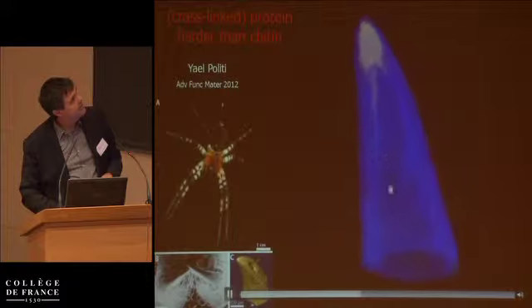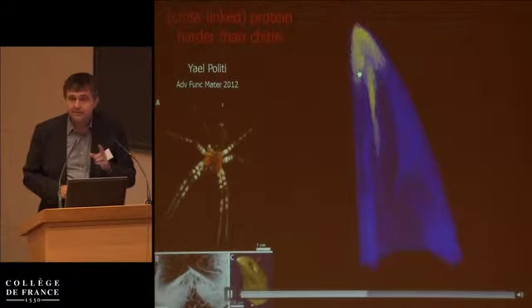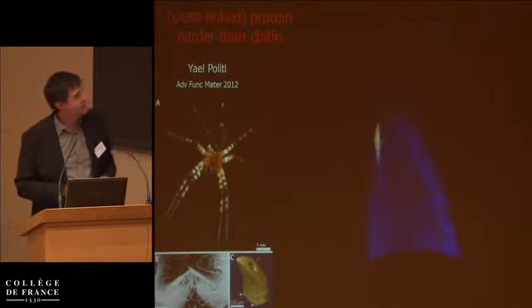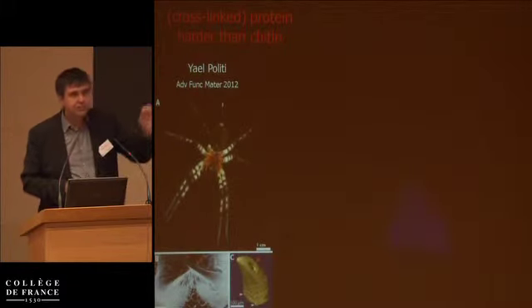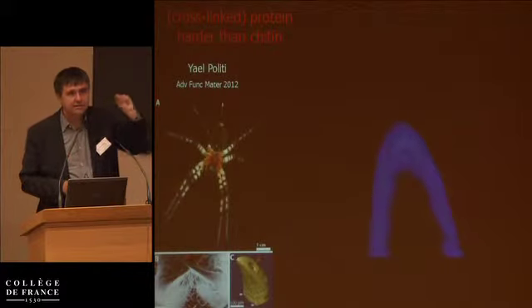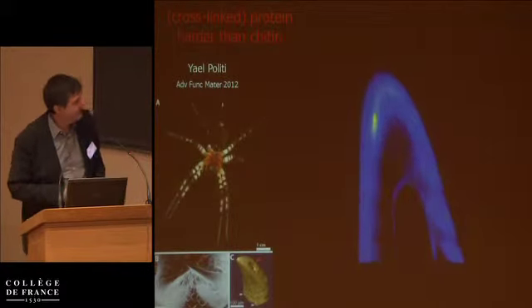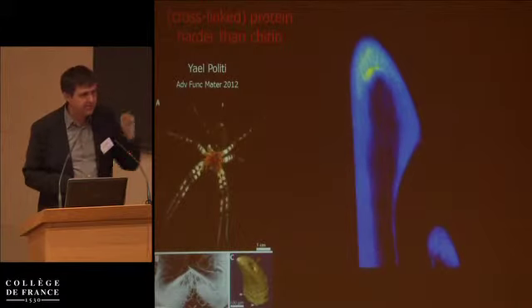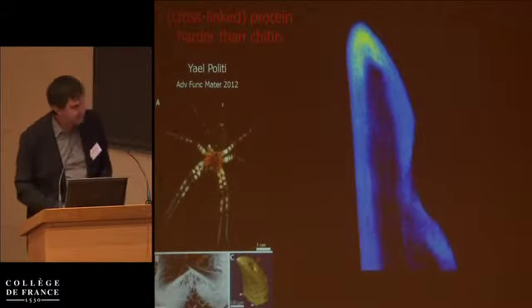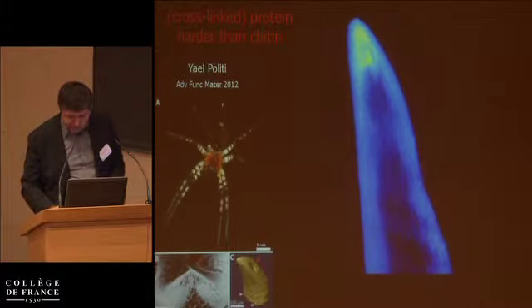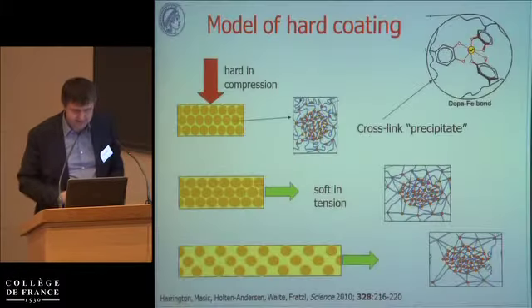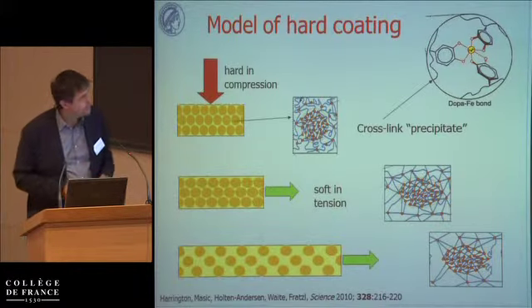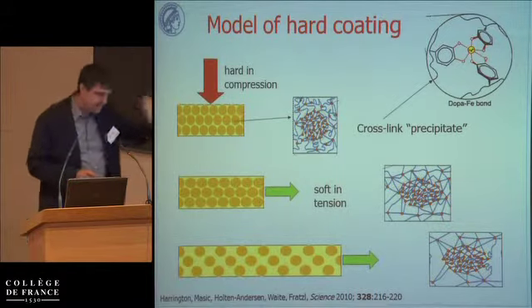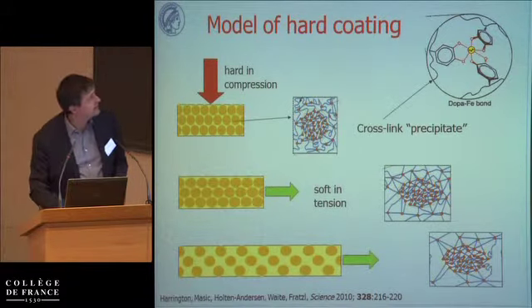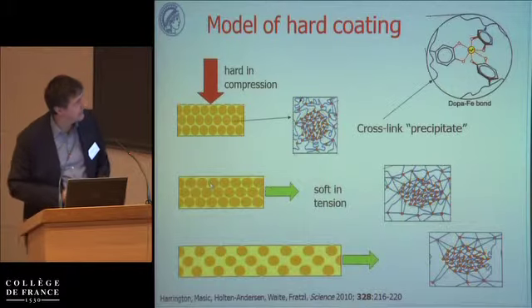And what you see here in this micro CT is the distribution of zinc. It's again the zinc histidine that I was talking about earlier. And in fact, the zinc cross-linked protein is harder than the chitin, and that's actually the hard tip of that injection needle that is penetrating the chitin carapace of the insect or the other arthropod that this spider is eating. So now back, this was just a small remark, and so these spheres are also very hard.